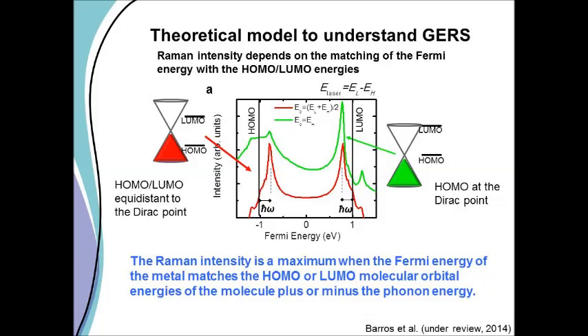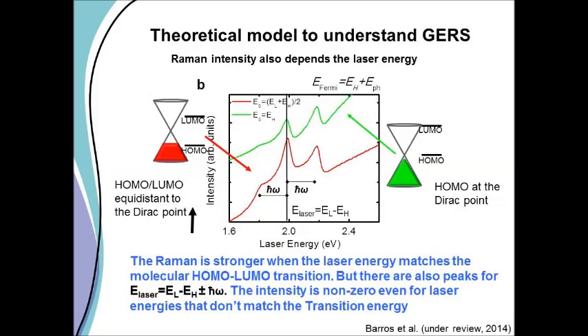So that's basically what our model is, and when that happens, it shows that we could either add a phonon or subtract one, and we get an extra peak. And that's where the extra effect occurs relative to the laser energy. So the prediction is that plus or minus the phonon energy is where we should see the enhancement, and that's where we observe it experimentally. And we could observe it by changing laser excitation energy, so we get that peak moving in energy space.